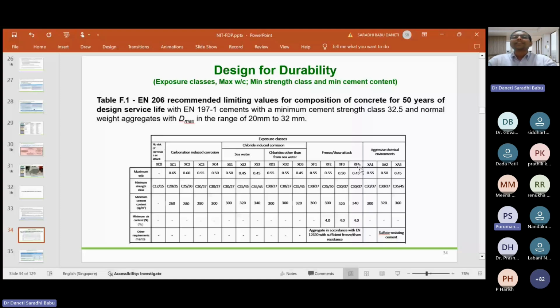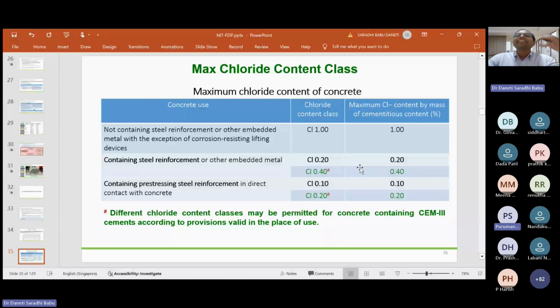Okay, if you look at the concrete quality, again you need to control the chloride content within the concrete. How much is the estimated chloride content? How can you estimate? Basically you have to know the chloride content of all the constituents involved in a given mix design for 1 cubic meter. So these chloride contents you need to control when it comes to reinforced concrete structures. Okay, for structural concrete you need to limit your chloride content to 0.2 percent by weight of the cementitious content. But when you are dealing with pre-stressing and post-tensioning scenarios, your chloride content is limited to 0.1% only. Okay, so in terms of expressing the chloride class, basically we go with Cl 0.2 for reinforced concrete, whereas Cl 0.1 for pre-stressed concrete construction.